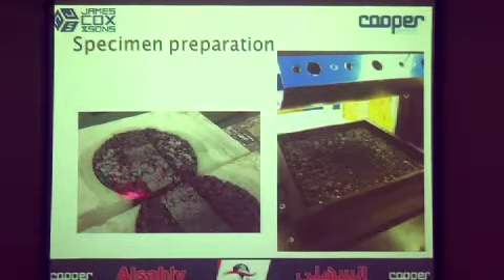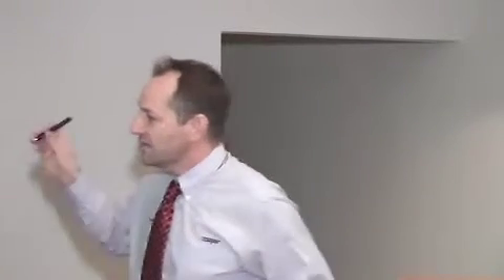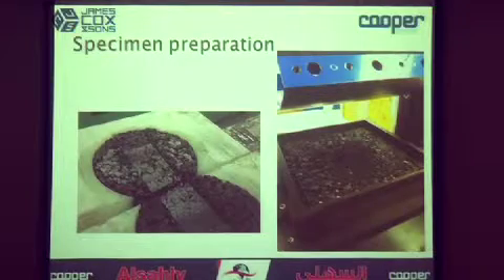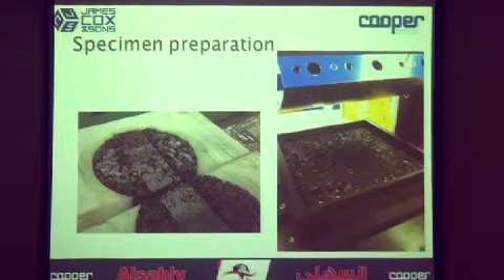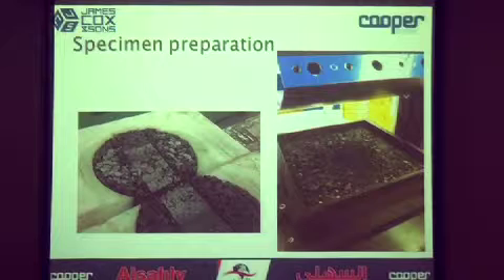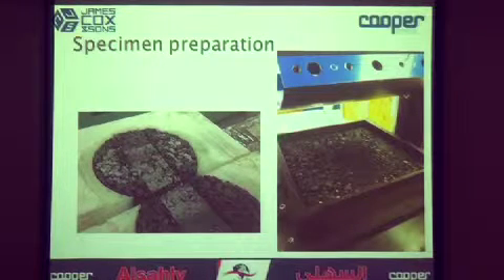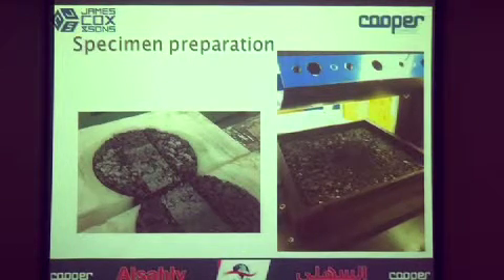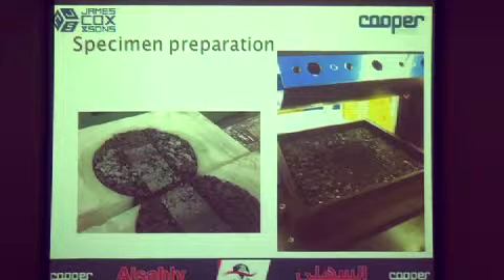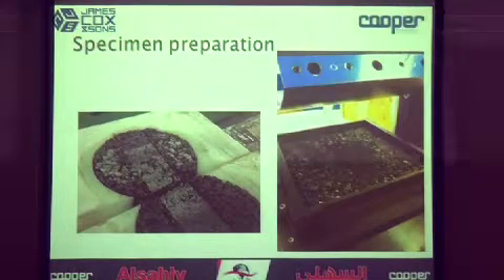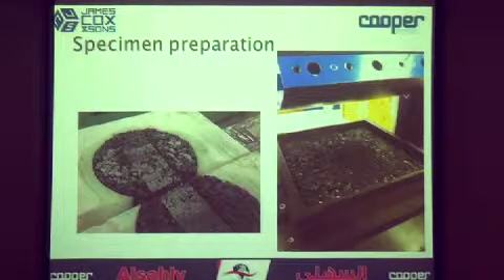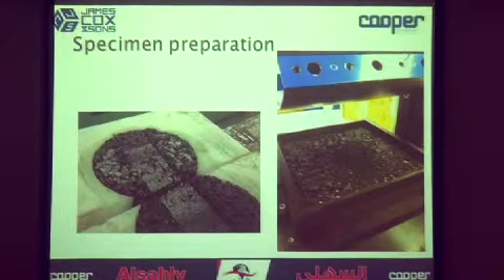This is what we saw downstairs in the labs. This is the AASHTO configuration that you get when you're doing Hamburg wheel tracking. Examples are cut from your gyratory specimen with a fine cut across. And in the States, they perform asphalt mixture testing on specimens made in the gyratory compactor. However, I wanted to show this, and this was yesterday.